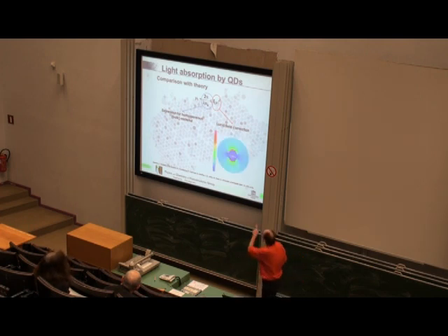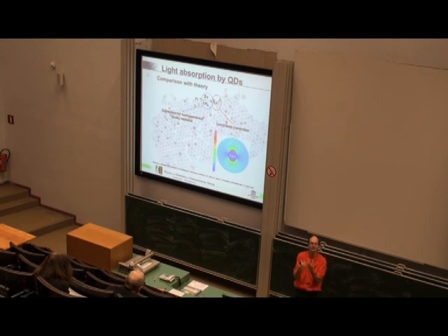The basic point is shown here. We have light, which is an optical electric field, and we have the nanocrystal. What we show here is the external electric field of the light. It's a color scale that gives you the field intensity. And what you see is we have a field intensity on our scale somewhere here for the incoming light. This is a driving field, right? If you look inside the particle, again, you have a homogeneous field, but its intensity is considerably lower. So this particle is kind of screening the electric field. The field cannot really penetrate the particle. What is important for the absorbance is, of course, this local field driving the absorption. So we need this correction factor if we want to calculate absorption coefficients.